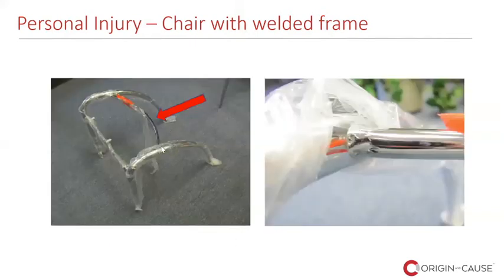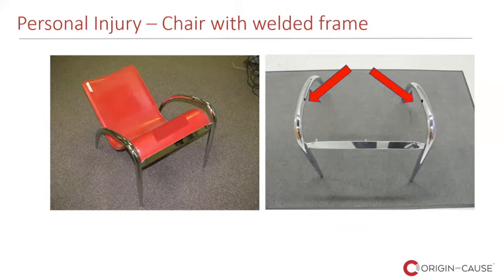As you can see in this image, the design provided that the seat is supported at the rear using a curved bar welded onto the frame. On the right side, it's a close-up view of a weld on a non-failed chair. This is a design deficiency, in my opinion, because people tend to sway when sitting on chairs, subjecting it to cyclic stresses. And on the incident chair, both welds gave way. You can see on the left side the collapsed seat, and on the right side the remaining frame with the locations of the failed welds.